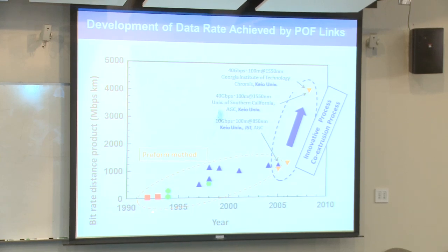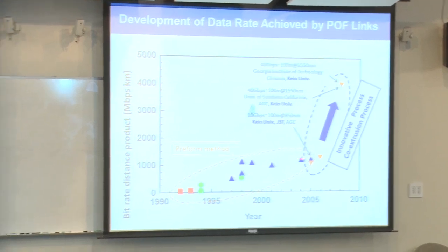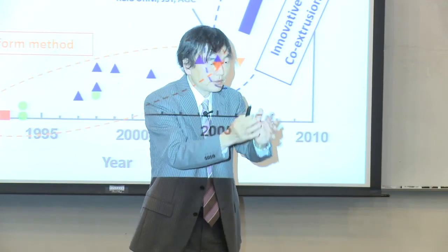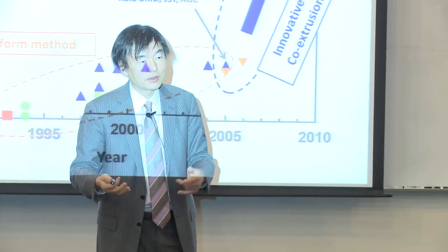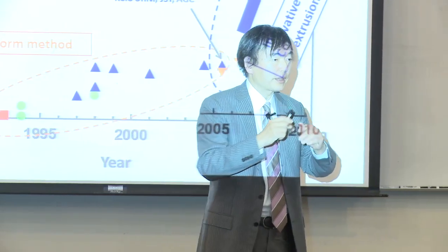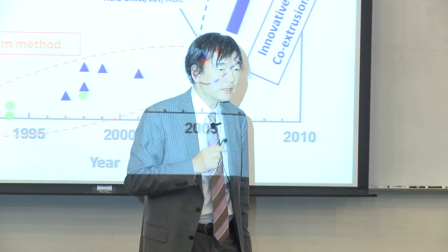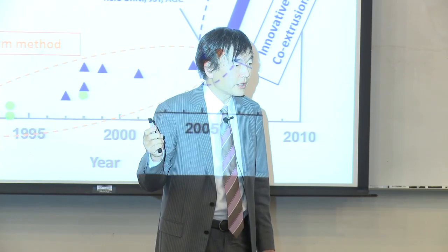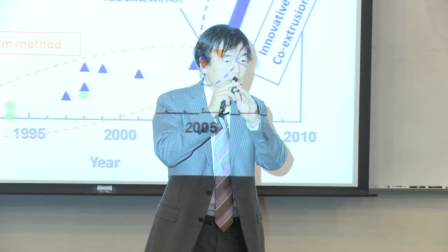And I suppose the preform method is much easier to control the index profile, because in the case of the co-extrusion process, what we can do is just do the extrusion. Then the diffusion of the dopant is based on the natural Fick's law. We cannot do any external control. But fortunately, the index profile by the co-extrusion process is exactly the same as the optimum index profile to minimize the modal dispersion in optical fiber communication. I don't know if there is such a relationship, but only God knows that the diffusion by Fick's law is exactly the same as the optimum index profile minimizing the modal dispersion.